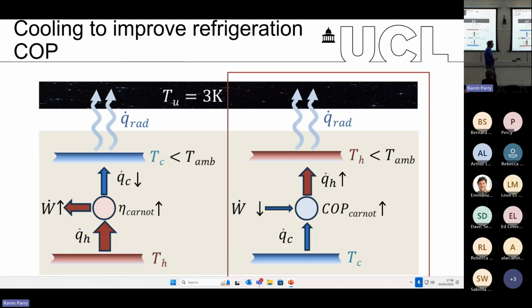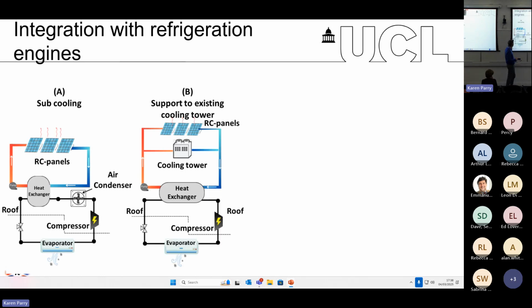Now, if we move to the refrigeration engines, here we have a complexity in that somehow we need to integrate radiative cooling, for example, with an AC unit. So these are two strategies that are typically employed. And now I'm going to give a second analogy with solar cells. In the field, a very popular solution is creating radiative cooling panels, in the same way as we have a solar panel, and rather than have electricity running through, we have water running through. So we have hot water on one end of the radiative cooling panel, cold water coming on the other end, and then coupling it via heat exchanger, for example, to an air condenser of a split AC unit. By the way, again, as a rule of thumb, for every degree of temperature drop on the air condenser, the efficiency of an AC unit improves by 3%.